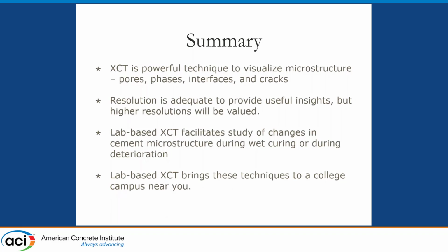And yeah, I forgot to mention this idea of doing wet studies. That certainly separates X-ray CT from SEM. With SEM, you'll only get dry samples generally, unless you use an environmental SEM. So if you want to do things that are in a wet condition, X-ray CT is a good option.